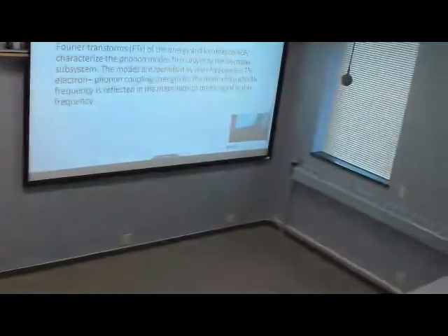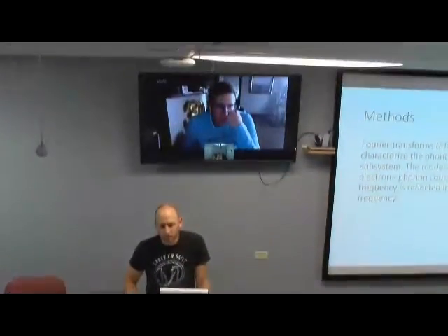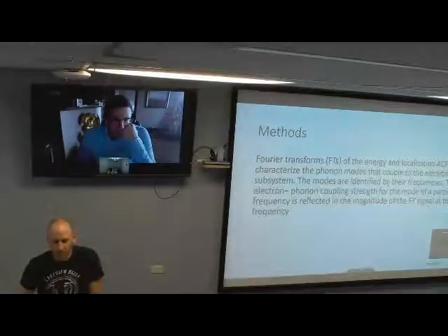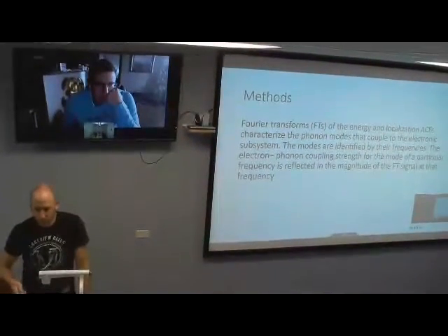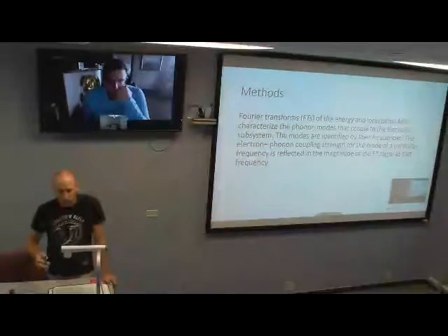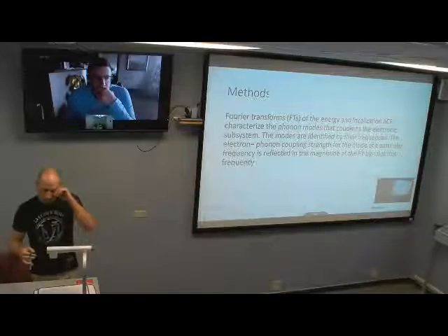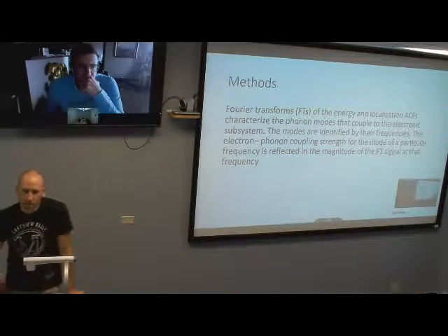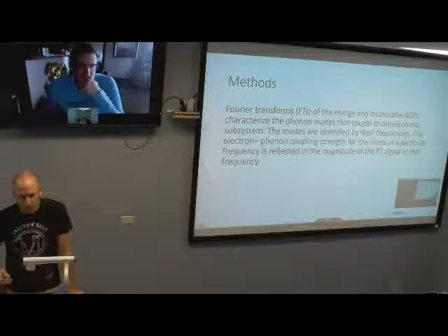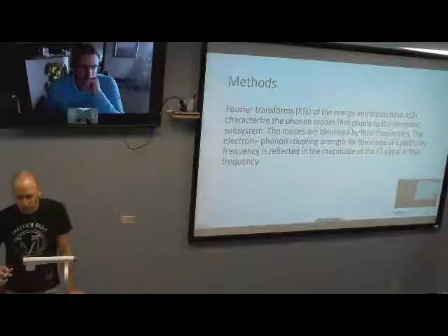Now, think about the dynamics for your systems. In this paper, they definitely do it not at zero Kelvin. They do dynamics at 300 Kelvin, room temperature. At 300 Kelvin you're probably still supposed to be close to equilibrium in these systems, but maybe there is already some tendency to go outside a little bit. So they first find not normal modes but actual frequencies, because if the motion is not harmonic, it's already included in their motion of nuclei at 300 Kelvin.